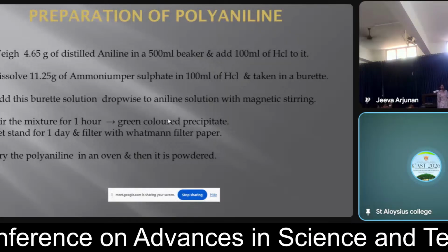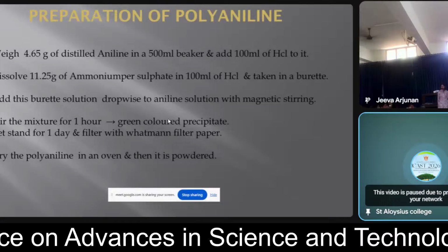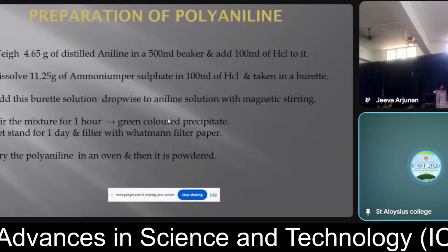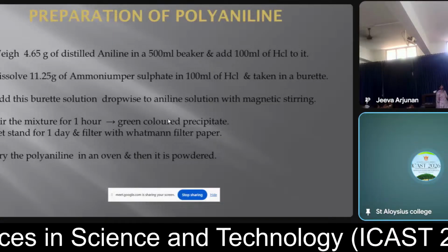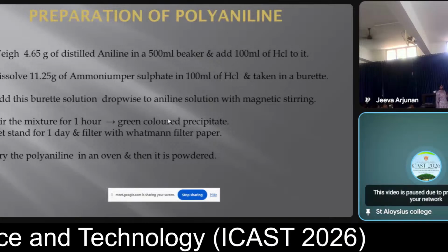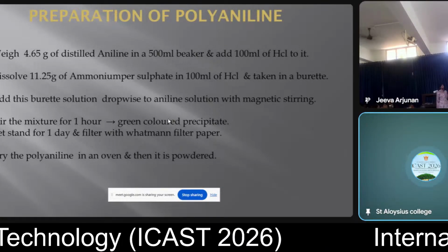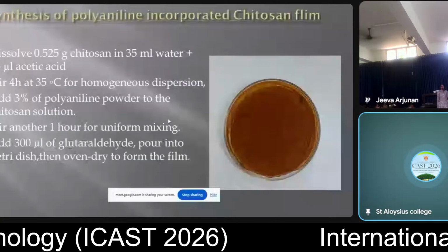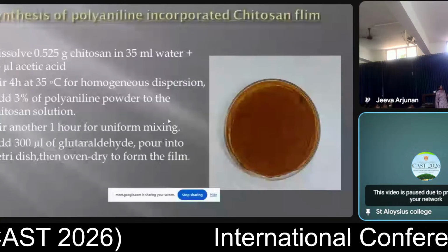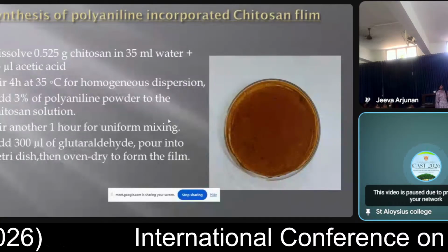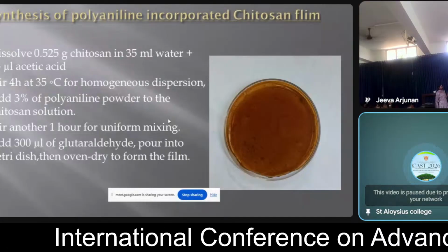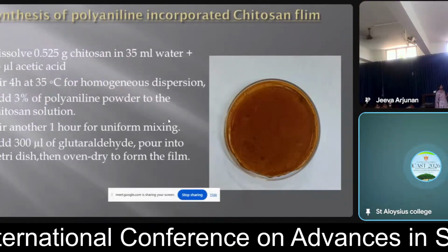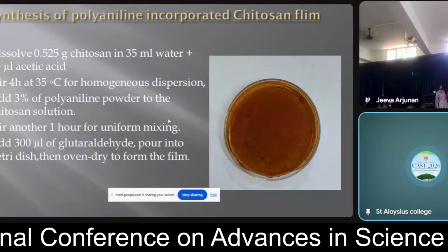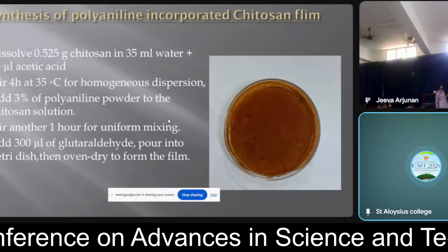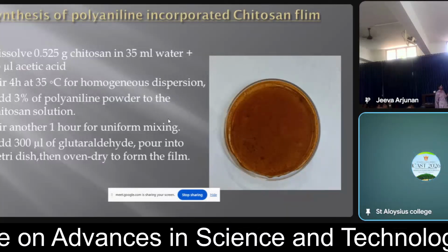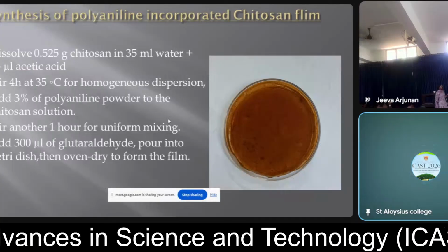For the synthesis of the composite, we put a definite amount of chitosan in water and acetic acid and stir it for 4 hours with a magnetic stirrer at 35 degrees Celsius. We add 3% of the polyaniline we prepared earlier, as powder, into the chitosan solution and stir for another hour for uniform mixing. We add 300 µl of glutaraldehyde and pour it into a petri dish immediately to form the film. This is what we got.